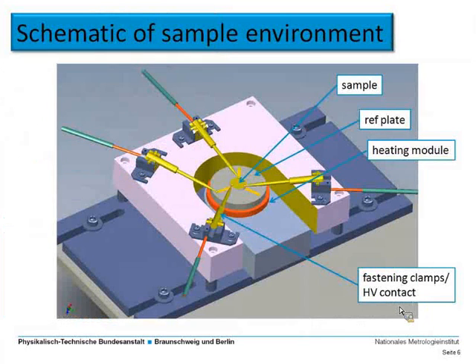So a little bit more detailed view of the sample environment is shown here. Again, you can recognize the sample disk in the center, then the reference plate with these gold stripes as a 3-point support. Then you can see those fastening clamps, which are used to keep the sample in place without constraining it considerably. And they also serve the purpose as high voltage contacts because somehow we have to apply the field to the sample. And below all of that, the heating module is indicated.